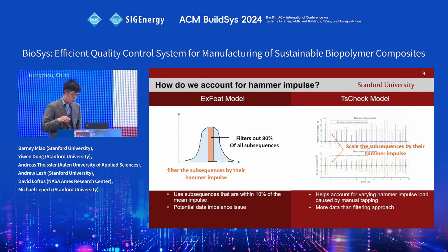When you do that, you filter out approximately 80% of the subsequences, which has some issues in terms of potential data imbalances when you train. So that is one issue of this approach, but it's the quick and dirty one. And in our more sophisticated model, that is much better.